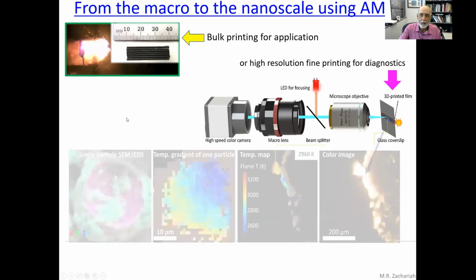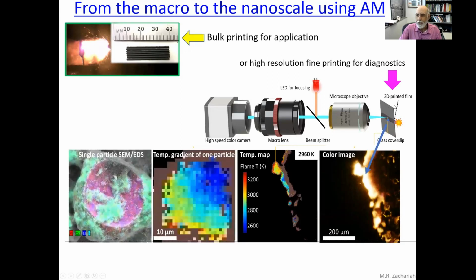And the last topic I'm going to talk about is direct imaging of the reaction front in 3D printed composites. How do you package these particles together? So here is printed material, and you can see the burning. But what we'd like to do is look microscopically. And so what we have is we print it now onto a glass slide, and we do microscopy on this. And what we'll get is images of the reaction front. Since this is the color camera, we can convert this into pyrometry to get the temperature. And you can see we can get a gradient within a particle to get things like heat fluxes.